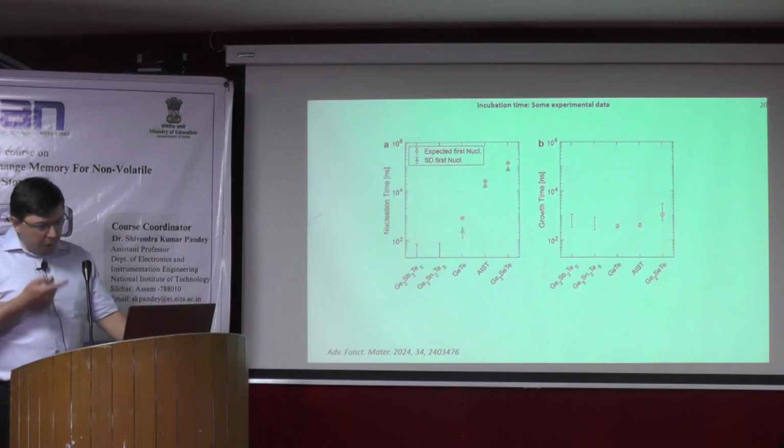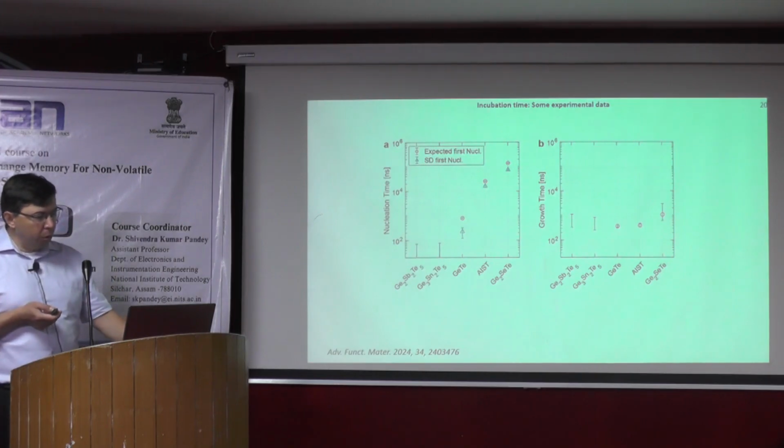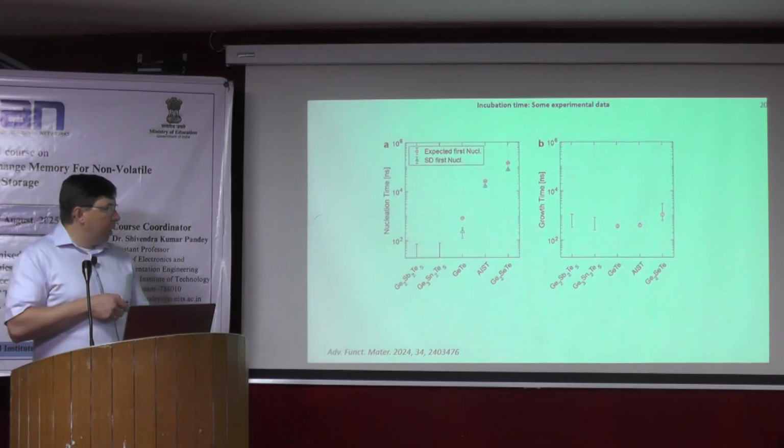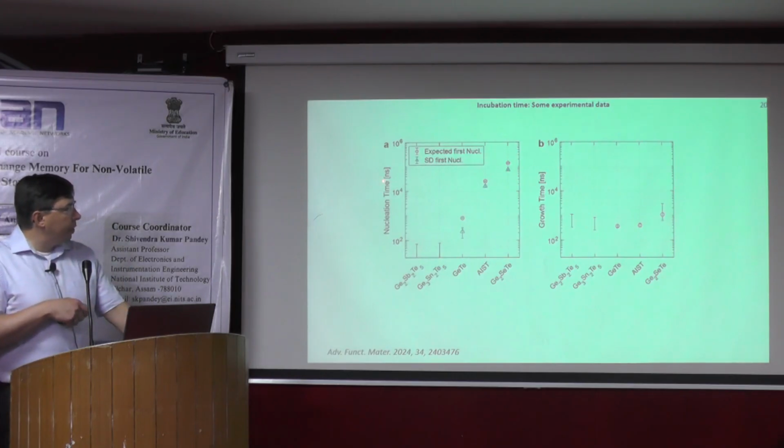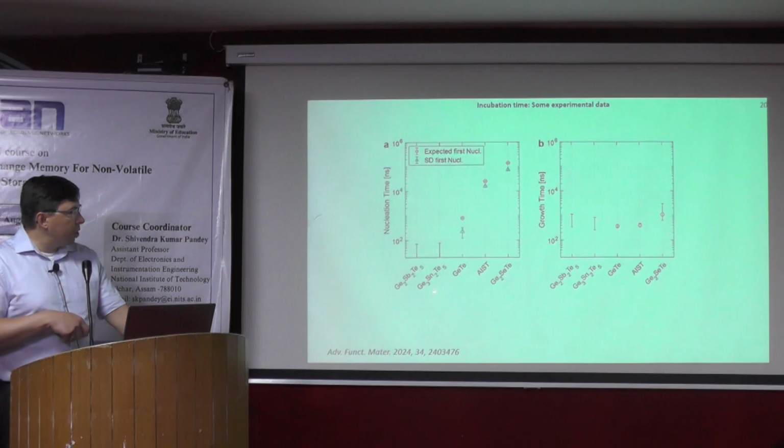The results are very interesting from my point of view, because first we found that the nucleation time of nucleation-dominated materials is very short. It is shorter compared to the growth-dominated materials, but the growth time did not change a lot for all compositions.